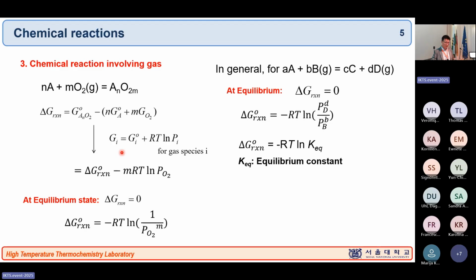So how can you actually decide that? The Gibbs energy of any gas species, in solution or in the pure state, is its standard Gibbs energy at the 1 atm condition plus RT ln partial pressure. And partial pressure, of course, is the mole fraction times the total pressure. Okay, so that's why the Gibbs energy of this oxygen can be changed now depending on your environmental condition.